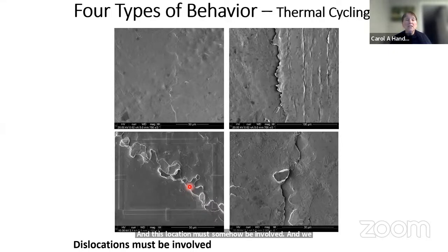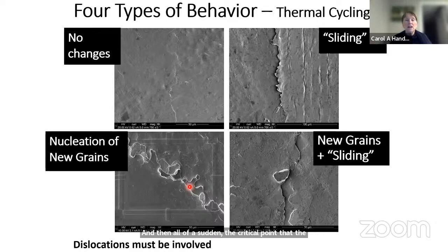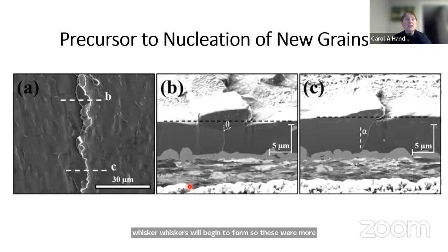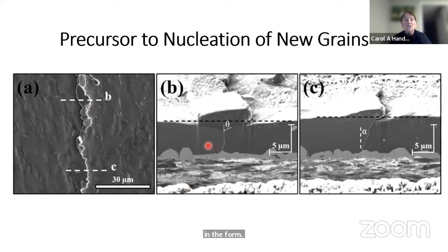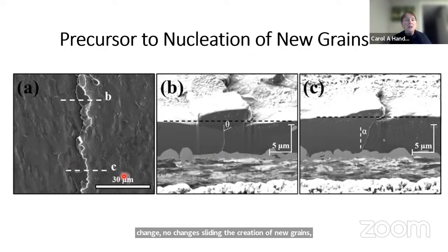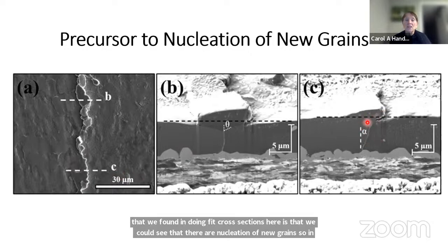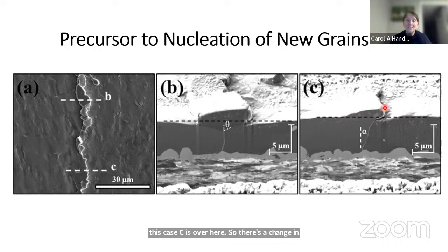And we think they're also involved in the polycrystalline thin films and columnar systems, because you can see that there won't be whiskers forming, and then all of a sudden at a critical point, the whiskers will begin to form. So these were 4 different phenomena that we saw: no changes, sliding, nucleation of new grains, and then combinations of the two. And one of the key things that we found in doing FIB cross sections here is that we could see that there was nucleation of new grains. So in this case, C is over here. So there's a change in orientation here. The top surface is tilting up, and as it tilts up, this tilting up corresponds to actually a change in orientation and it must be happening by accretion of dislocations in here.